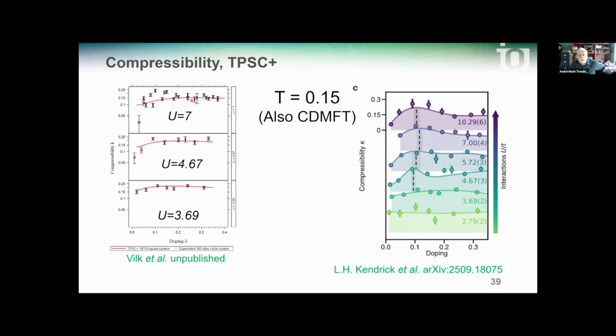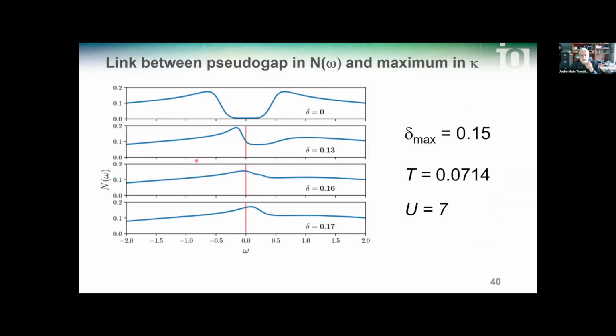Here's a comparison on the left between the cold atom data and a calculation by Yuri shown with the red line using this improved version of TPSC. The first temperature where the maximum was observed in the CDMFT calculation turns out to be the same as the one here. In the low interaction regime, the pseudogap is a precursor of the spin density wave ground state. This plot illustrates that the maximum compressibility is at a doping that corresponds closely to the place where the pseudogap disappears in the density of states.